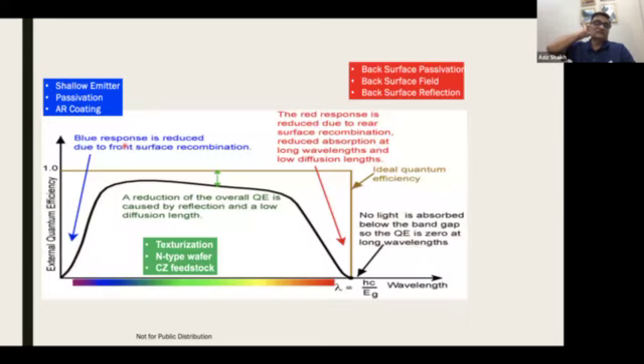Okay. So this is another chart, and this is also interesting because, like I said, you can have a quantum efficiency, meaning you can collect 100% of the electrons, if you didn't have all these dangling bonds. So on the front side, you lose some collection, on the back side, you lose some collection, and in the middle, you lose it because there are intrinsic defects. And then, of course, after a certain wavelength, if the lambda is too high, then the energy is too low, so you are not going to excite any charge carriers. So that has been the fundamental behind the solar cell efficiency.